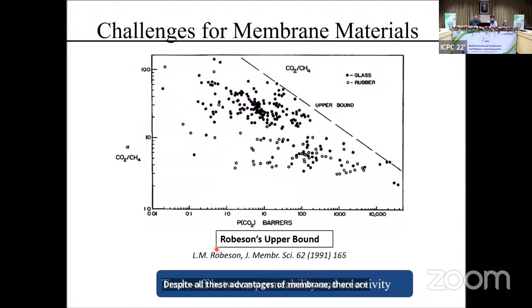One of these challenges was presented by Robeson in 1991 when he plotted all the available materials, which are mostly polymers, whether glassy polymer or rubbery polymer, for a certain gas separation. In this case, the application is CO2 removal from natural gas, CO2/CH4. On the y-axis, you can see the selectivity of the gas, and on the x-axis, the permeability or the flux of the gas. Mr. Robeson concluded that for all the materials that have been discovered so far, there exists a trade-off. The materials that have high selectivity have low permeability. The materials that are highly permeable have low selectivity.